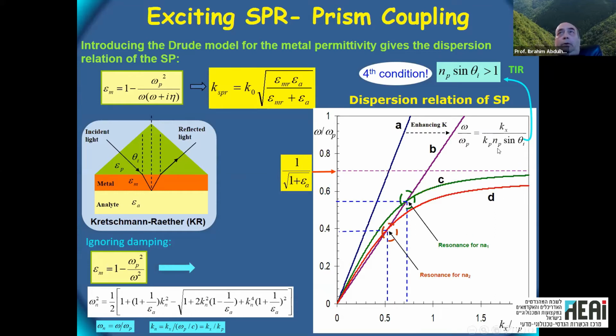Okay? So if we do that with a prism, we can easily write omega normalized to omega p, like the kx normalized to kp. And here we have sine of the angle inside the prism. If we choose a prism with large enough refractive index, then we can get this slope here small enough to get intersection with the dispersion curve of the plasmon. So the condition for excitation will be met at this point. If we change the refractive index of the analyte, it will shift to this point.